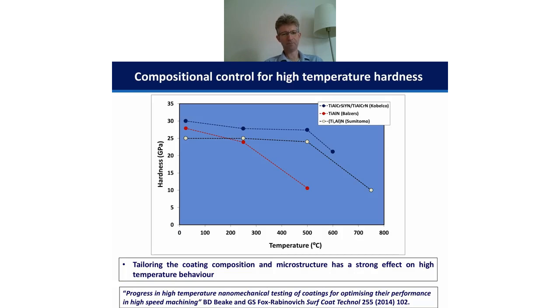Another example here showing 3 different titanium aluminium nitride based coating systems, and what we can see is that the curve in red, which typically looks almost as good as the others and better than this one at room temperature, actually has much worse thermal stability than the other coatings. And we can see really when the temperatures in the application due to friction are very high, then you need this high temperature hardness and you need this high temperature yield strength of these guys, and this one is much worse. And this again correlated to the coating performance in these continuous turning tests.